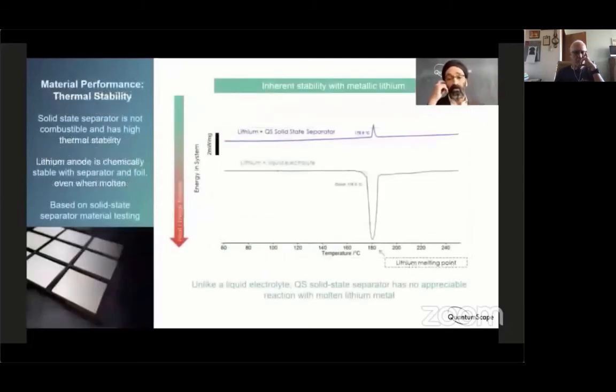And finally, to address the safety issue, this is a test called a DSC test, which stands for differential scanning calorimetry. And really all it is, you take a lithium metal, put it in direct contact with either a liquid electrolyte or in our case, a solid state separator, and heat up the pair of materials. And what you see is with the liquid plus lithium scenario, when you get to lithium melting temperatures of around 180 degrees Celsius, you see a massive exothermic reaction, which corresponds to a fire.